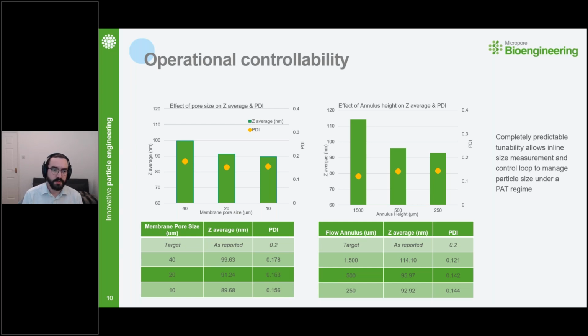So as you can see, changing the pore size there gives us a change in the size on the left, and changing the annulus size, effectively changing the shear or the velocity within the channel inside the device, we're also able to change the size of the particles that we're producing as well. This has given us a really predictable system to allow for easy inline adjustments. As we said, we think this can really be integrated quite well into manufacturing facilities that are using things like PAT.